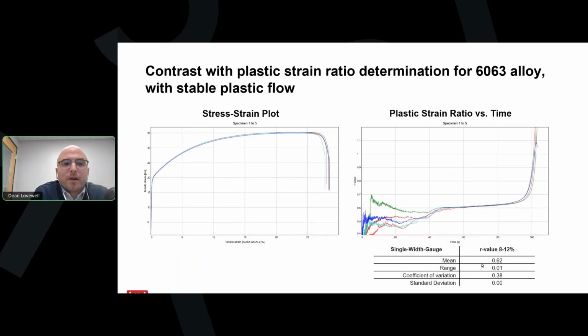And then for contrast, I wanted to show a similar test that was done on a 6000 series alloy. Specifically, this is 6063, and it does not exhibit the PLC effect. As I mentioned before, though, it unfortunately doesn't exhibit a lot of work hardening. For this alloy, we see smooth stress strain plots and the accompanying smooth R value determinations with very little variation in plastic strain ratio test to test. The coefficient of variation for R value for this alloy is just 0.38, so much lower than what we saw for that 5182 alloy.